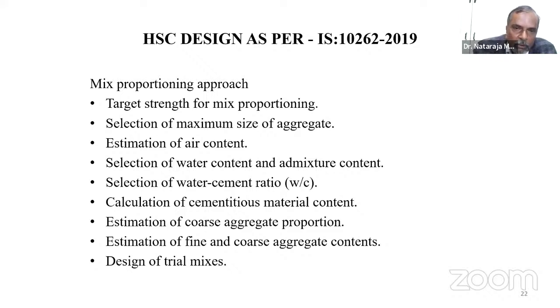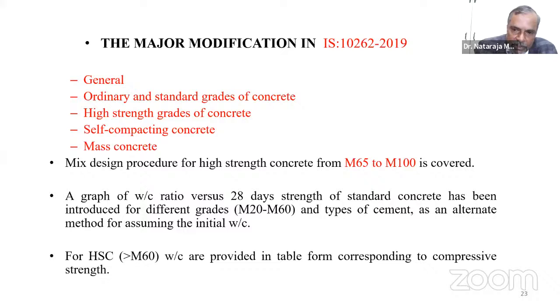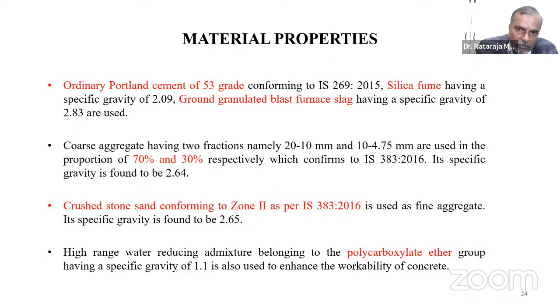Since you're all the faculty, I'm not going into the details as to what this mix design is all about. And of course, M65 to M100 is what the concrete mix design is covering. High strength concrete means 65 and above only, as far as the current code is concerned. And we have used IS 269:2015, again the latest code, where 53 grade cement is permitted, silica fume with a specific gravity of 2.09, and GGBFS with a specific gravity of 2.83, and 70% of the bigger aggregate, 20 to 10 size, and 30% of the lower size, 10 to 4.75.